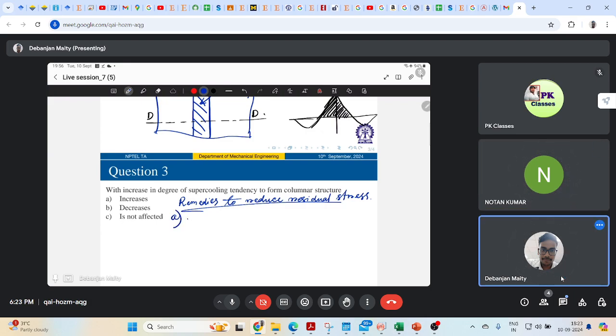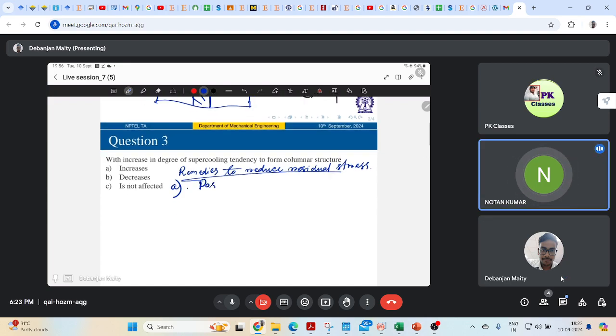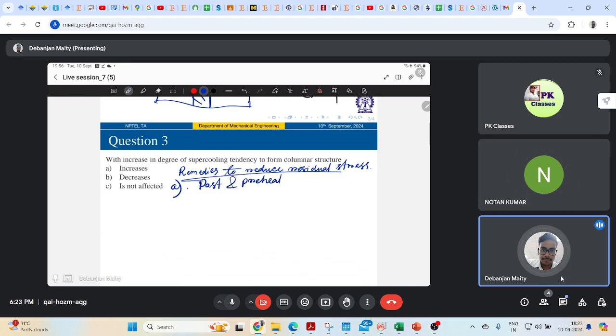Tensile residual stresses will decrease with post and preheating. Anything else? You can do something called stress relief annealing. Everything depends on how much time you are heating up. So soaking time is important in your heat treatment method, right? In stress relief annealing, you are heating metal to a specific temperature below its melting point, holding it for a period of time, followed by slow cooling. So what will it do?